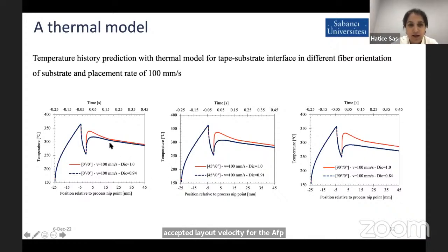And you can see how the final degree of intimate contact is changing the thermal profile, meaning that with this thermal contact resistance, with higher ply orientation changes, we are going to have a drop in the temperature. So that might be one of the reasons for having a lower degree of crystallinity or lower fusion bonding mechanisms